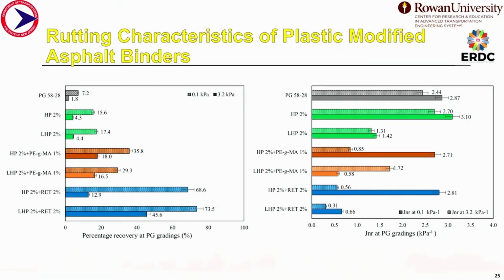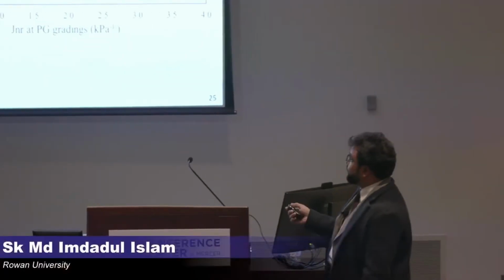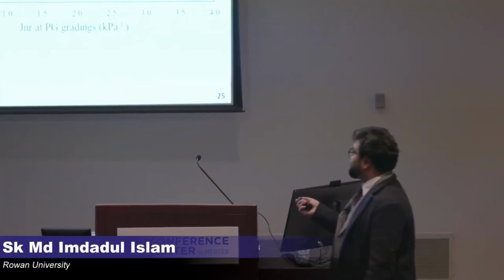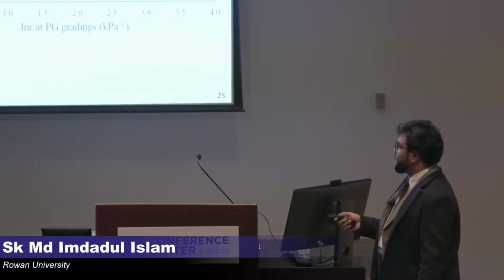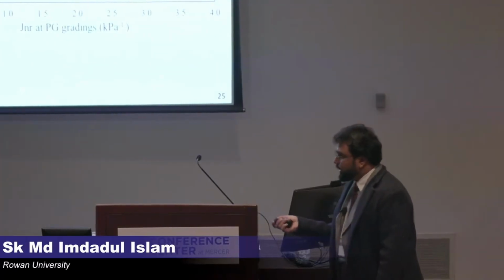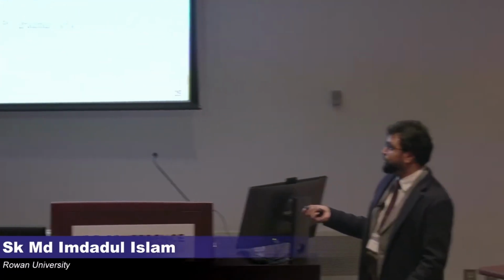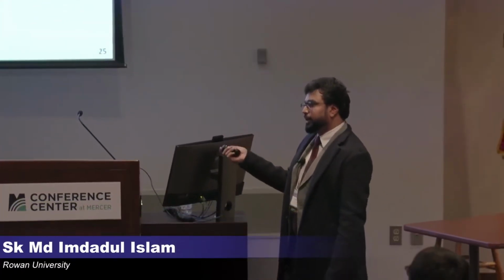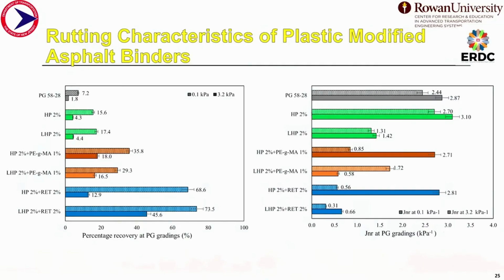To further assess the performance at high temperature, we did the rutting characteristics analysis using the multiple stress creep recovery test, where we get the percentage recovery and the JNR value, which is non-recoverable creep compliance. The higher the percentage recovery is for a polymer modified binder, the better the performance of that binder at high temperature or in rutting resistance. From here, we can clearly see with the virgin binder and with the plastics, if we go down with the stabilizers, the percentage recovery is increasing with both HP and LHP plastic, where again LHP 2% plastic with RET is showing higher results in percentage recovery.